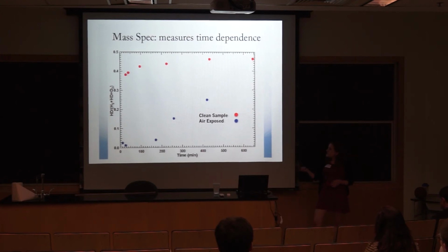So there's still a little bit. You'd expect that a few metals might still be open and the reaction would still happen, but the rate is much decreased. Then we just wanted to make sure that we could recover our sample. We heated it up to get all the water out, and we got back to what we had before.